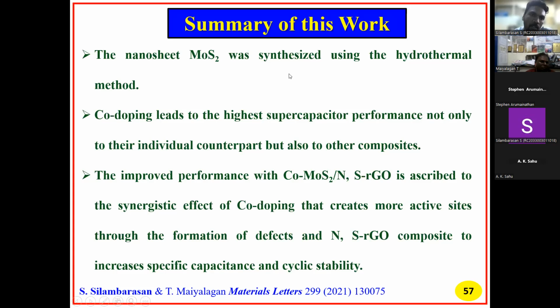Next, the summary of this work: the nanosheet of MoS2 was synthesized using the hydrothermal method. The cobalt doping leads to the highest supercapacitor performance, and not only the individual component but also other compositions improve the performance. The improved performance of the composite is ascribed to the synergetic effect, and the cobalt doping creates more active sites through the formation of defects.